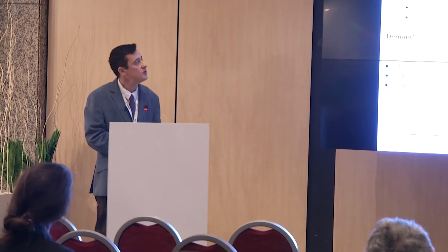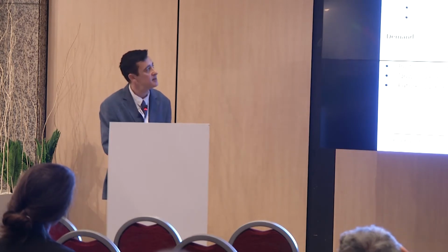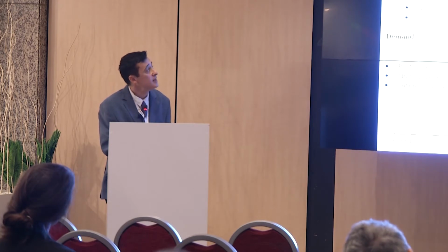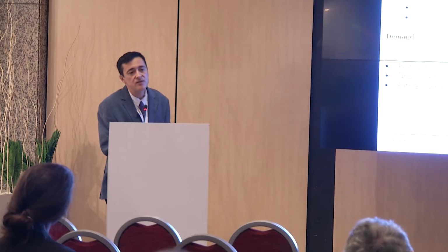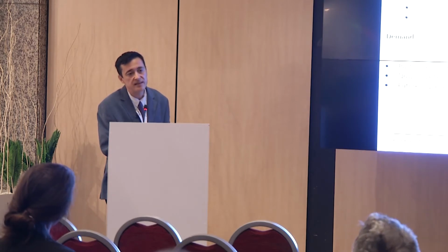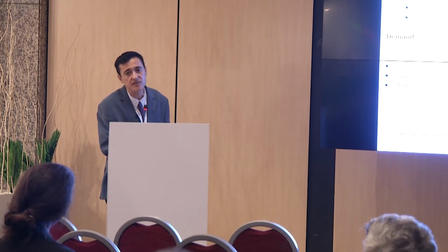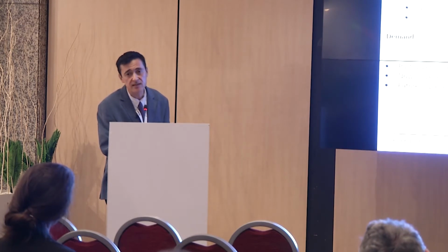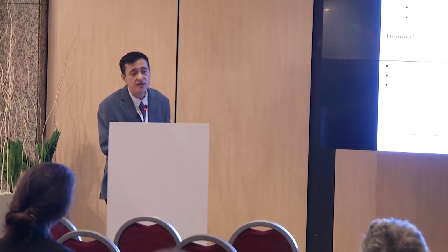There are some demands coming from the producers. They want to have a high TG value. It was not accepted to have this level of TG values in the past. After doing the coating, color fastness, xenon arc or UV accelerated weathering tests are showing us a gloss loss. So they want to have a low level of color fastness, and it needs to be suitable for isothermal curing. They do not want to heat up and they do not want to cool down.